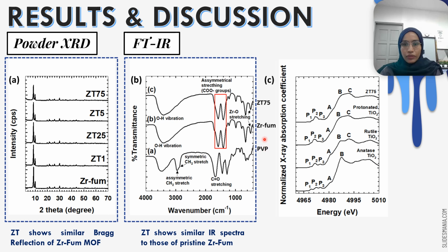Okay, as you can see from here, there is a PVP. The PVP here, I forgot to mention in the previous preparation method. I used PVP as an additive or stabilizing agent in order to produce nanoparticles. Even though there is an addition of PVP, we can see that there is no detection of PVP at all in the samples of nanohybrid. The ZT nanohybrid shows similar IR spectra to those of the pristine zirconium fumarate.